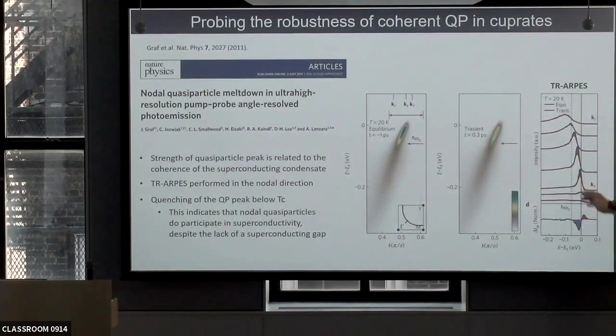What was surprising at this stage was really to see that what looks like the amplitude of the quasi-particle is coming down. But it's something to be discussed. Okay, but that's the result: there's a pump excitation, which causes apparently the amplitude of the quasi-particle peak to decrease. And that's done below TC. This is done below TC. Correct? This is done at 20 Kelvin.